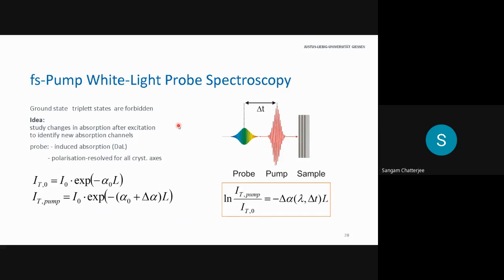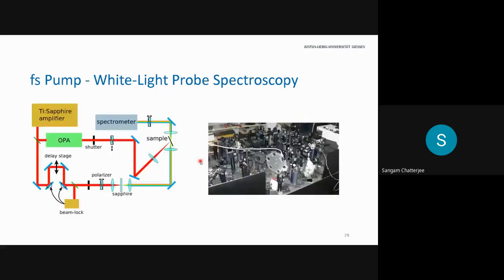So to study the system, we did pump and probe spectroscopy, which means we excite the system using a laser and measure the transmission. This is a differential technique, so we can actually measure the changes to the transmission only. This makes this virtually background free. And using polarization, we can do this on all crystalline axes on all samples. It's a rather complicated setup, to give you an impression.